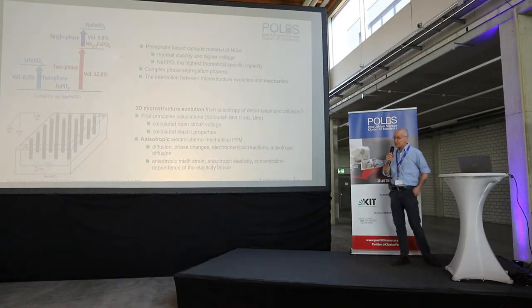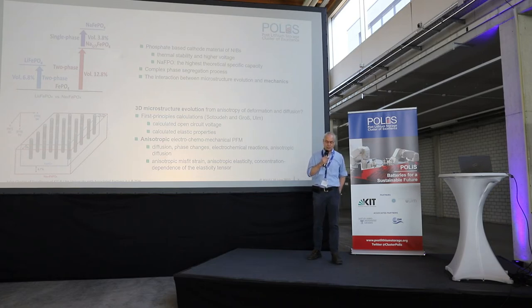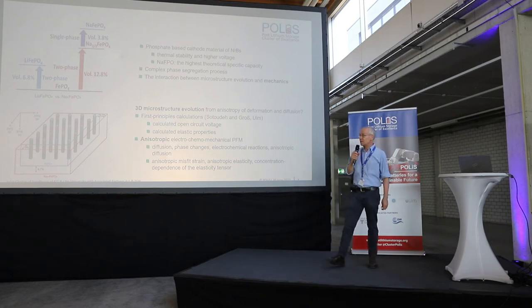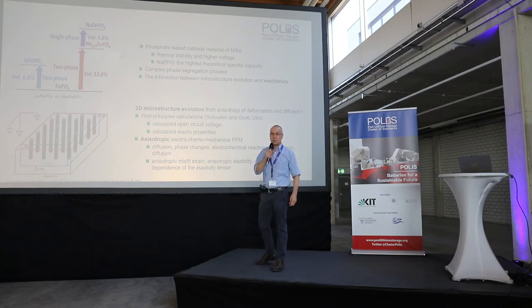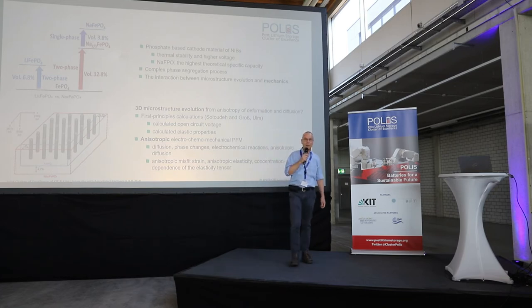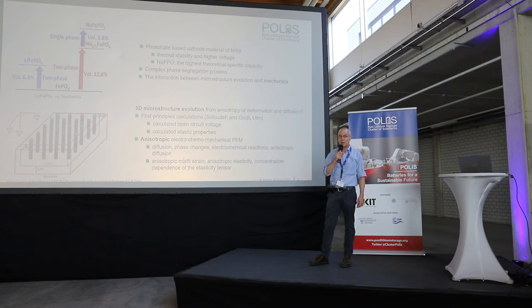So, the basic idea of this work is to couple together density functional theory and phase field modeling to put up a multi, or let's say, bi-scale simulation chain. And the research subject here in this case was sodium iron phosphate, which shows, in contrast to its lithium counterpart, quite complex phase segregation behavior, where we have this interesting two-third intermediate phase, which was shown earlier by simulation work of Tao, maybe occurring also because of mechanical reasons in order to reduce mechanical stresses that occur in the material